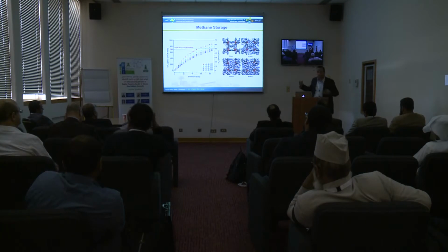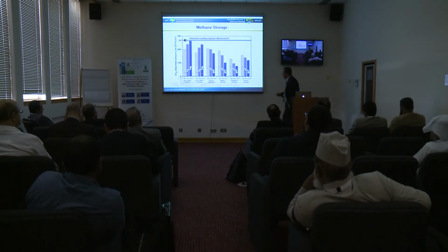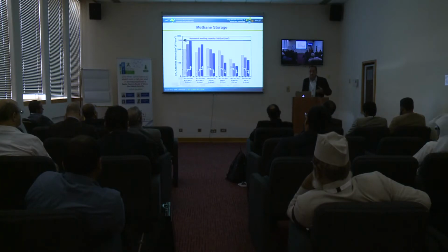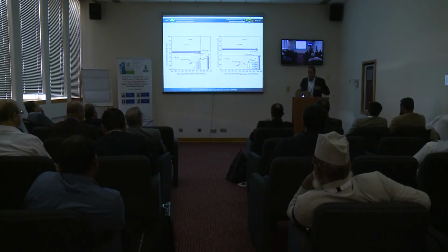And again, it's at low temperature, but the concept here is that this material allows you to store a large amount of methane. And most importantly, as opposed to other materials, when you lower your temperature, you are actually increasing the working capacity of this material due to weak interactions of methane at the surface at low loading, below 5 bar. So quickly, just how this stands without going into detail. This material has a trade-off between volumetric and gravimetric. We also did simulation studies where we changed our organic linker, and you can see here that this material is actually better for methane.